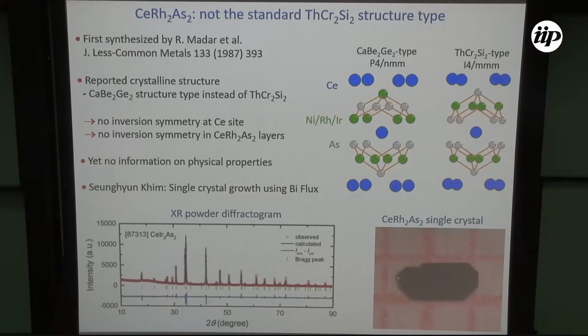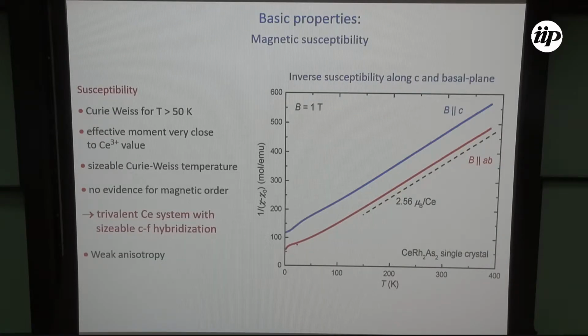Here is a picture of the first single crystals we got, quite nice facets, but quite small. Meanwhile, they are a little bit larger. That's an X-ray powder diffractogram, which confirms that we have indeed this structure and not this structure, and that the compound is pretty pure. So the first thing you do if you have a new compound of this kind is look at the susceptibility, because that tells you whether cerium is 3+, intermediate valent, or 4+.